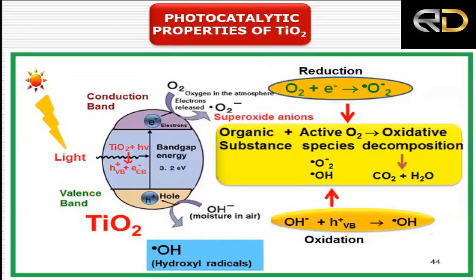it is washed away. The titanium dioxide is known as wide band gap semiconductor with 3.2 electron volt energy gap, band gap. Now, when ultraviolet light comes, the electron from the valence band jumps to the conduction band and a positive hole is created here. An electron goes there. This electron converts the oxygen molecule in the atmosphere to oxide radical, superoxide anion, and this is converted to hydroxide. And these superoxide anions and hydroxide radicals, they react with the organic matters, decompose into carbon dioxide and water, and with the water or with air, they are washed away.